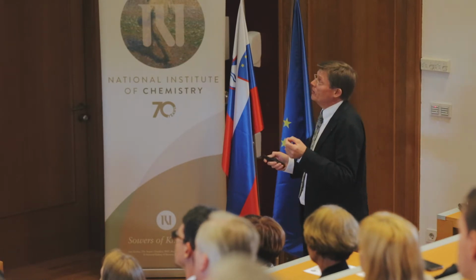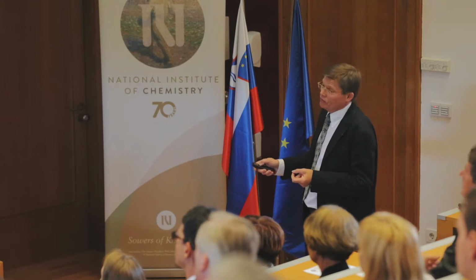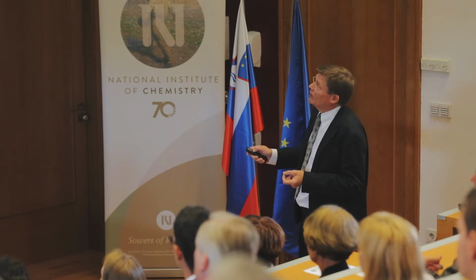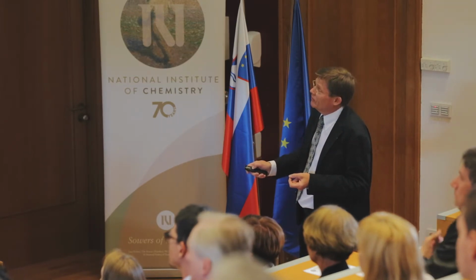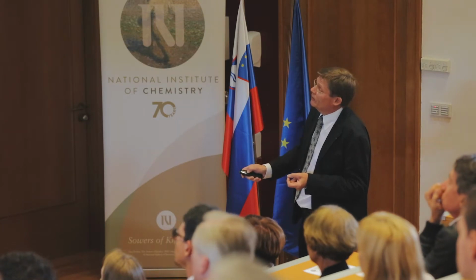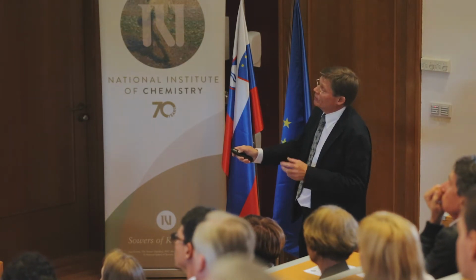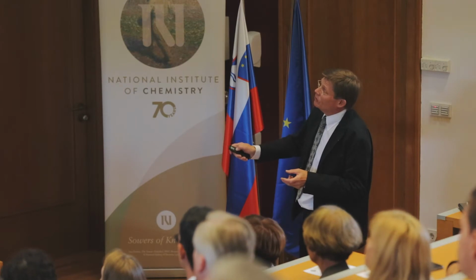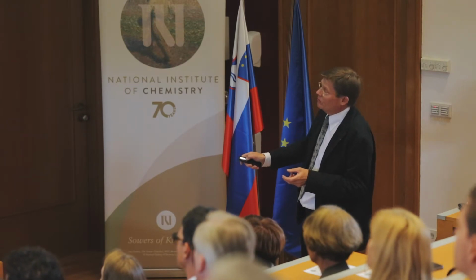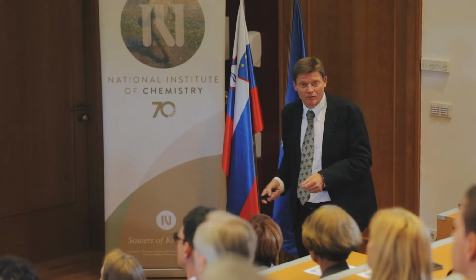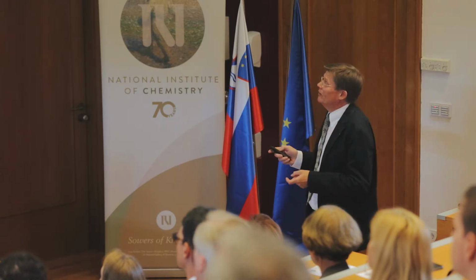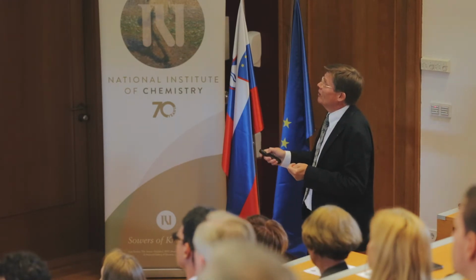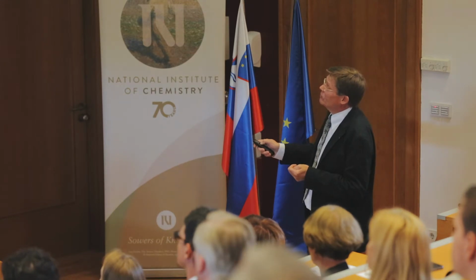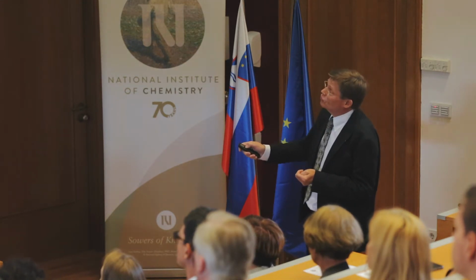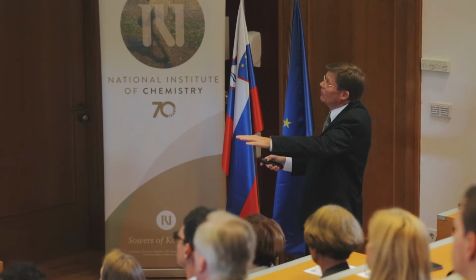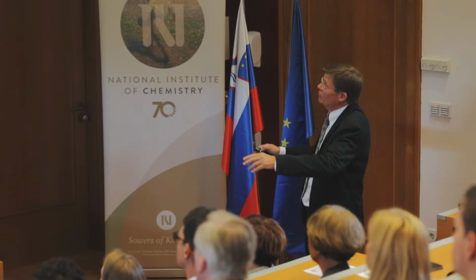First, real mapping in terms of impedance spectroscopy, in one of our next papers. The ions move in this direction. They are blocked here. The electrons come from here. They're blocked there. And in between, you can store lithium, and this is again taken account of in the circuit. Don't look at the details, just realize how interesting it is. And finally, there is a capacitive response, because you cannot draw a steady state current through a battery without changing composition.